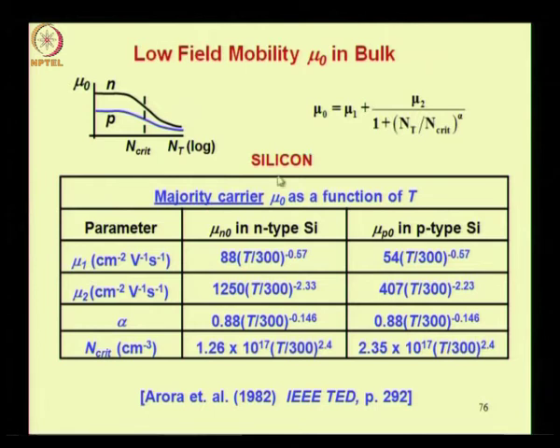Now let me just mention the significance of the n critical. Okay. So what is the significance of n critical? You see, when nt is equal to n critical, the mobility is approximately half of the maximum value. If you leave out this mu1, which is a small quantity, you can see here, so mu1 at room temperature is about 88 for electrons in silicon, and mu2 is 1250. So this is really a small value, the value to which the mobility saturates here. So approximately for nt equal to n critical, your mobility falls to half of the maximum value.